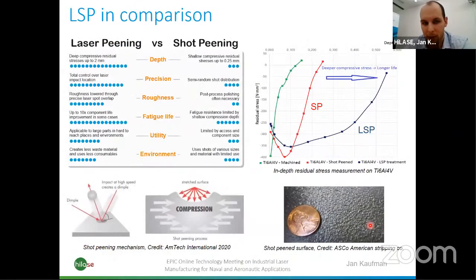The closest thing we have to laser shock peening in industry right now would be shot peening, which is very similar, but instead of laser pulses, you use high velocity balls that basically hit the material and create this dimple, this plastic deformation, which again causes the compression underneath. There are a few key differences between these two technologies. The first one, I'd like to point out, is that the compression depth caused by LSP, laser shock peening, is much, much higher than with shot peening. It's usually up to a few millimeters, say 1 to 3 millimeters. This really depends on the material and its thickness, while in the case of shot peening, it's very superficial. It's just the surface, basically.